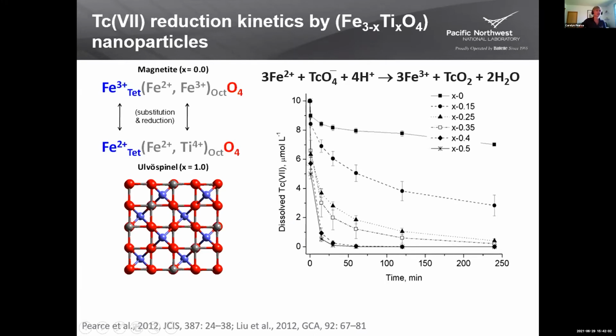And so this is the reactivity part. These are batch sorption experiments conducted over a period of minutes, which was only possible by synthesizing those nanomagnetic particles to give that high surface area, and then do due diligence to make sure that they were the same structures as we were seeing in our minerals from the site.